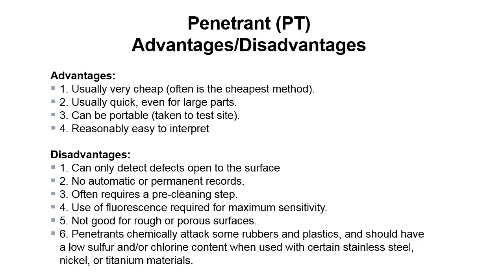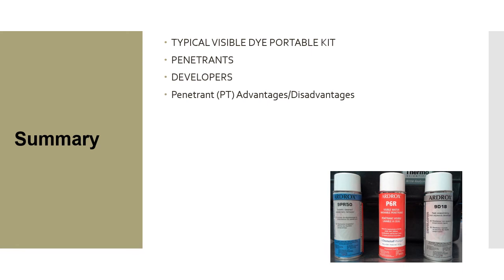Advantages and disadvantages of penetrant testing: Advantages — usually very cheap, often the cheapest method; usually quick, even for large parts; can be portable and taken to a test site; reasonably easy to interpret. Disadvantages — can only detect defects open to the surface; no automatic or permanent records unlike x-ray film; often requires a pre-cleaning step; use of fluorescence required for maximum sensitivity; not suitable for rough or porous surfaces; penetrants chemically attack some rubbers and plastics; and should have low sulfur or chlorine content when used with certain stainless steels, nickel, or titanium alloys. In this module, we touched on typical visible dye penetrant portable kits, penetrants, developers, and the advantages of penetrant testing.